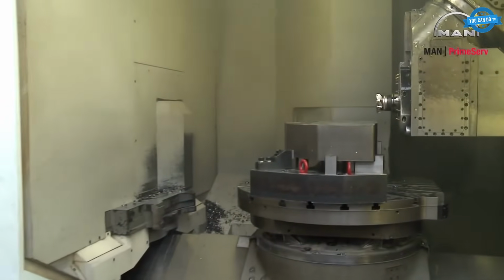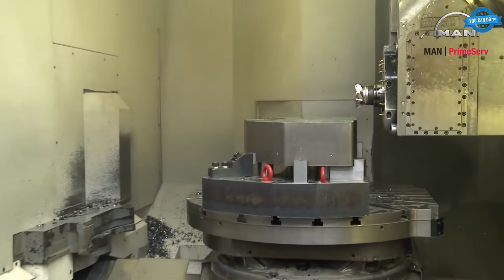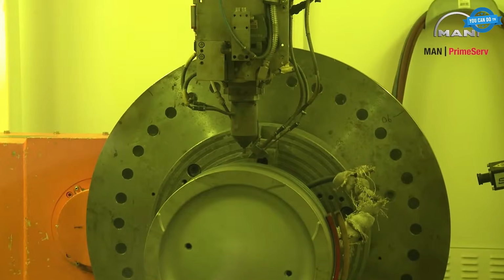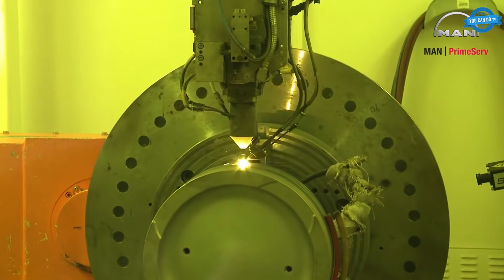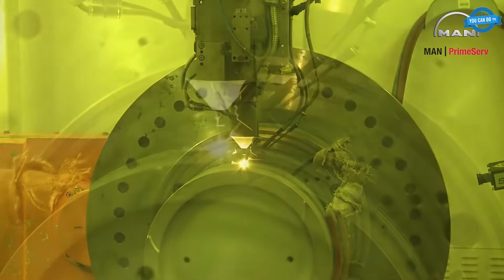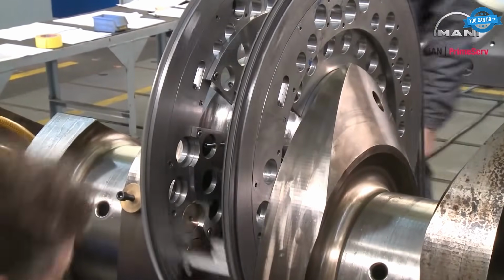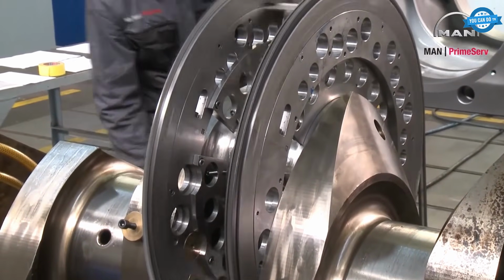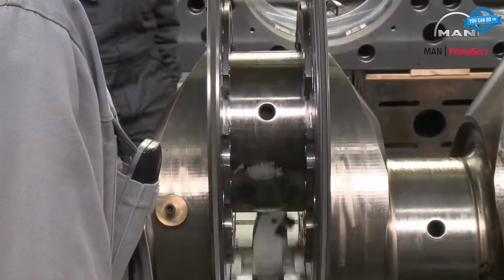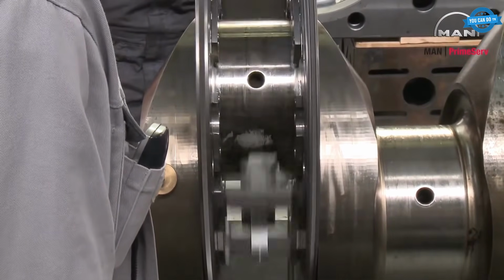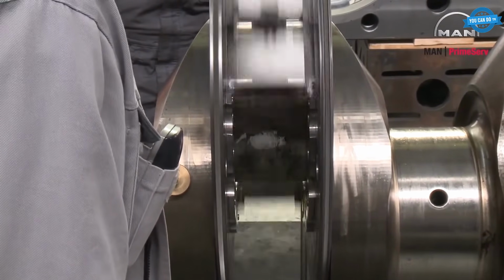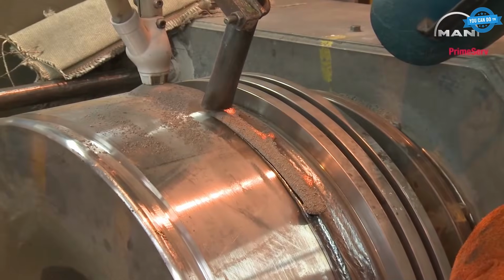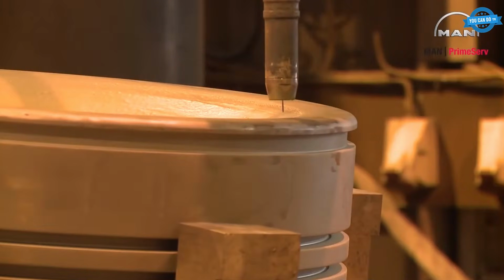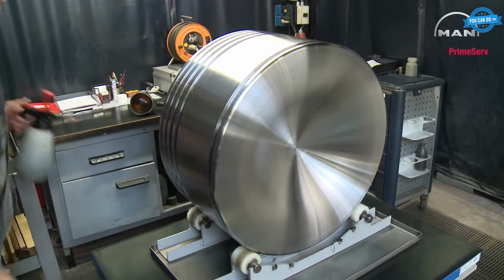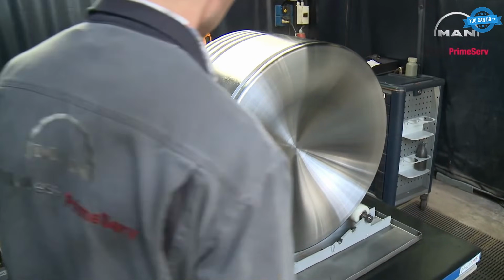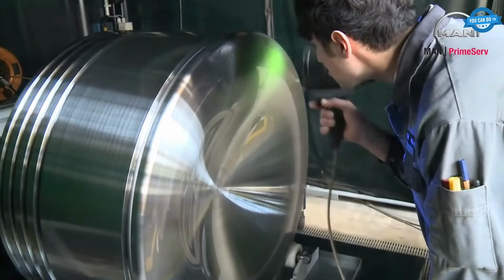Nearby, a cooling jacket is being repaired and a cylinder block reassembled, both of them parts that live under constant heat and pressure cycles. Damaged crankshafts can even be reduced and rebuilt inside the engine using tailor-made tooling. Direct testing follows every repair, and different welding processes restore the worn metal because a part allowed back to sea has to be trusted not to fail mid-voyage.